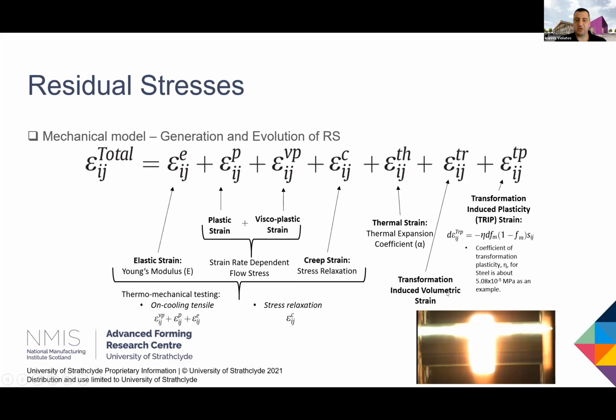Obviously, I talked about the volumetric strain with the transformation induced from austenite to bainitic in this specific case. It is not that easy to get martensitic formation with this specific alloy, at least not for the cooling rates that we are experiencing. Obviously, carbon diffusion between the stainless steel and the carbon steel can change things, but for this specific material it is much easier to have bainitic microstructures, and you will see the reason later on. Something that sometimes people have neglected is to include also the transformation-induced plasticity, a specific term just to accommodate the extra strain that comes from the phase transformation.